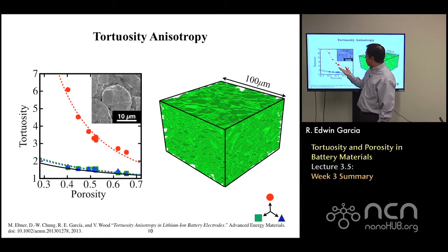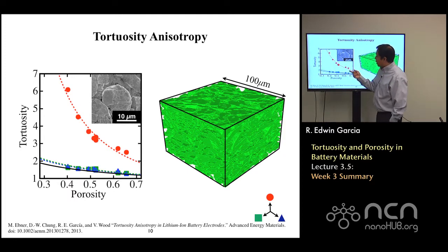The benefit of having perfectly spherical particles is that you can have a high reactivity per unit area and a lower tortuosity, while the high aspect ratio structures will allow you to pack more material, but the losses will be much higher in comparison.